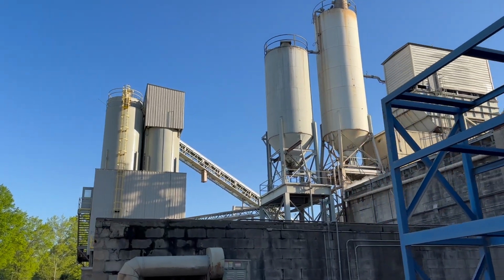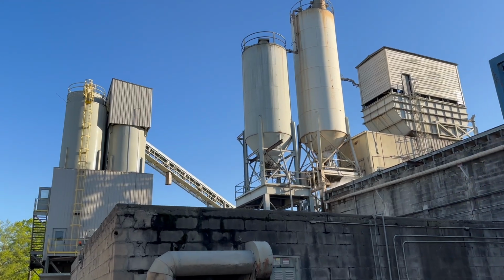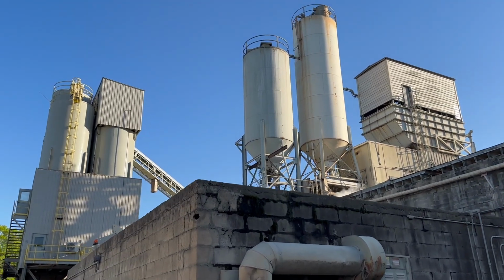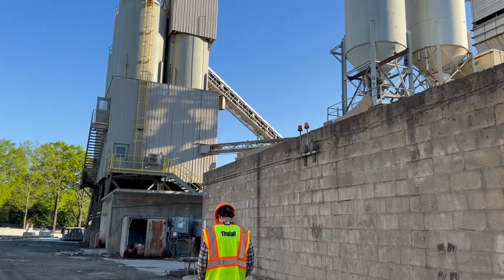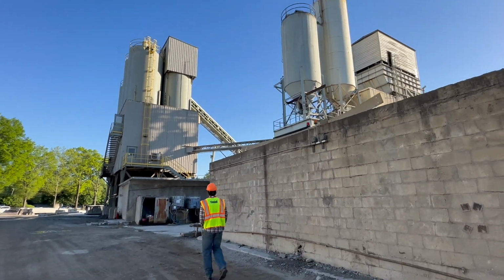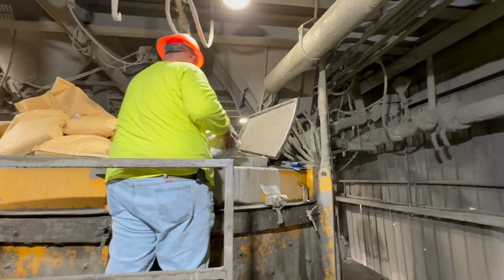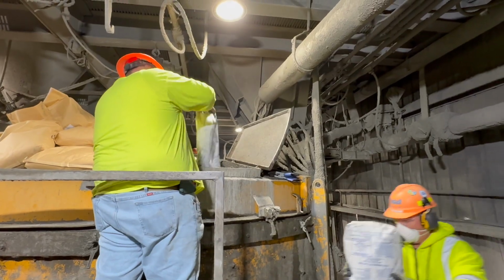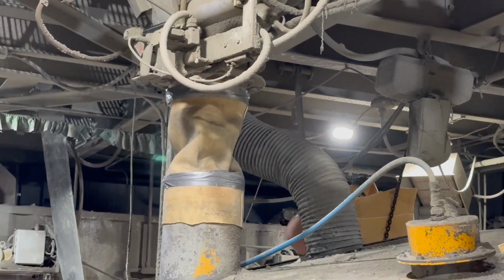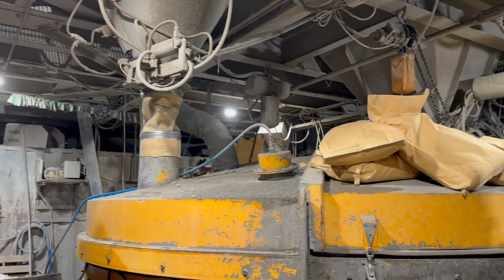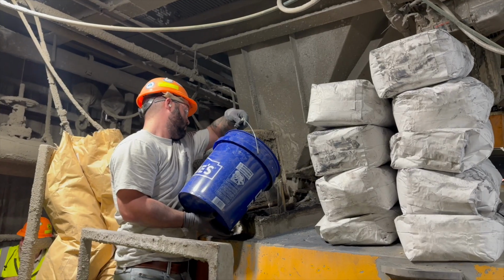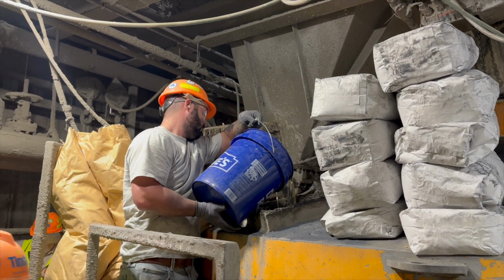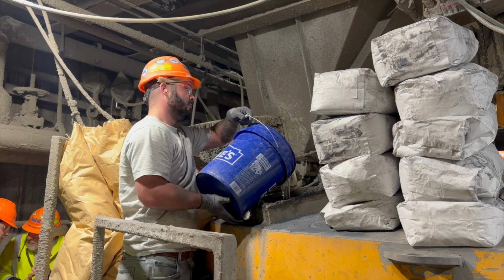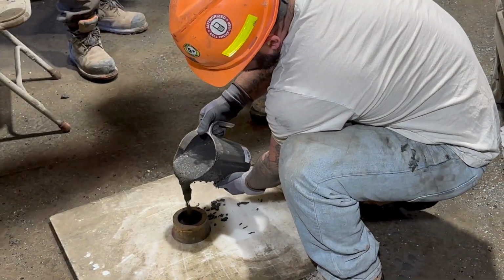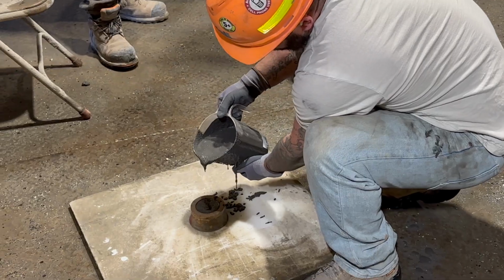Afterwards, we went over to the batching plant to begin mixing our UHPC. Sand had to be added to the mixture, along with about a third of the water that was going to be used. Silica fume was then added by hand and mixed with the sand, followed by the cement and most of the water, minus a few gallons that would be left out to leave room for adjustments. That's when the water reducer and hydration stabilizers were added manually, and a flow measurement was run to make sure we had about an 11-inch flow.